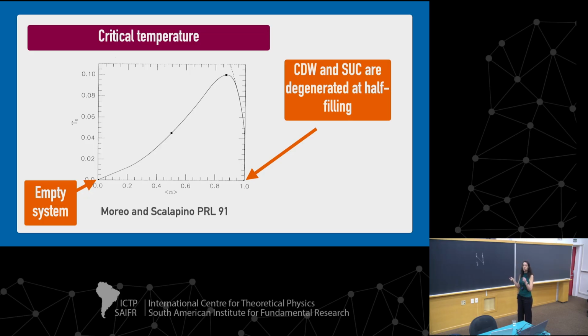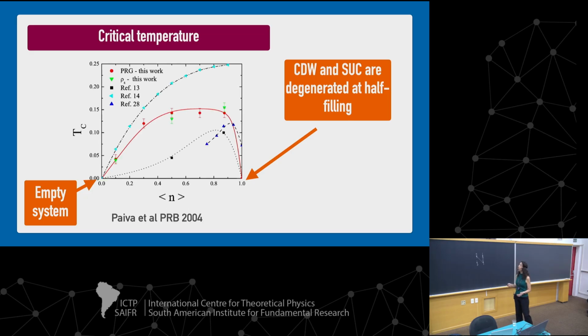But as soon as you dope it a little bit, they have different energies, and the charge density wave has higher energy, and you have superconductivity, superfluidity. So it's super fun. I've done this later and added more points, but the points here and here are really pinned. But it's important to have a good estimate of these temperatures.